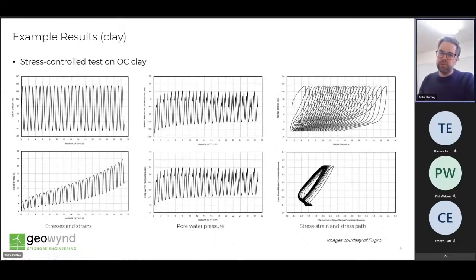Looking then at the results of another stress control test, this time on a low plasticity over consolidated clay, but a similar stress ratio as was applied for the normally consolidated clay, we see significantly larger cyclic pore water pressures and cyclic shear strains developed within the sample in this case. The pore pressure response is related to the tendency of the soil to dilate during shearing, and that creates a more significant loss of cyclic stiffness, as you can see from the stress strain characteristic response.